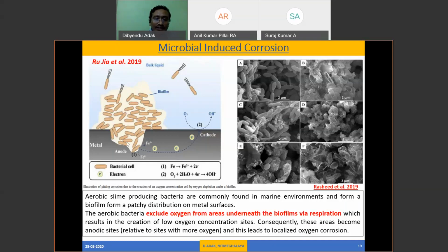If the oxygen concentration is less, then the electron transfer will be more. This will give the anodic action, and the reinforcement bar in the marine environment will give the cathodic action. So electron transfer will start. If the electron transfer starts, then corrosion will initiate, and by this mechanism they can corrode the reinforcement bar within 2 or 3 years, depending on the concentration of marine water, salt concentration or ion concentration. These are the feasible studies of how biofilm or bacterial cells are present in the corrosive zone.